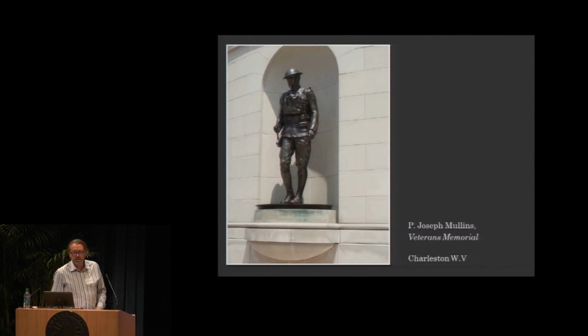And this is what it looked like about 5 hours later with the new coating applied. So we were actually able to treat this monument in 3 days. So in comparison to solvent cleaning, that would have taken quite a bit longer.